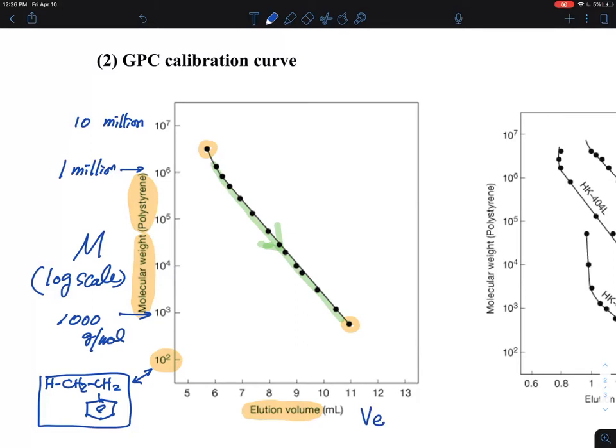So for the higher the molecular weight it is, this is a better way to look at it. By using the higher polymer with the higher molecular weight, they are making this polymer to be eluted at a shorter time, right? So if you are here, you are at the low molecular weight, your elution time is, let's say, 10, elution volume is 10 milliliters, and then if you go up to the high molecular weight, it comes out at 6 minutes, or 6 milliliters.